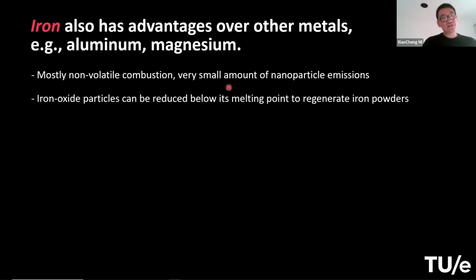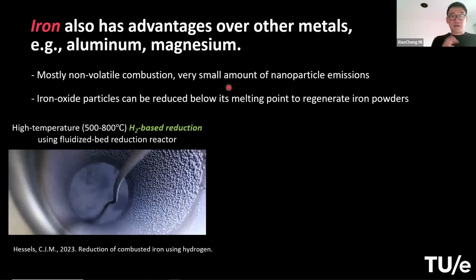The other advantage is that iron oxide after combustion can be reduced back to iron below the melting point. And that means this can be done either in solid phase or in a dissolved solution. And these are indeed the two technologies that our group is nowadays developing. One is using a relatively high temperature hydrogen-based reduction using a fluidized bed to reduce iron oxide back to iron.